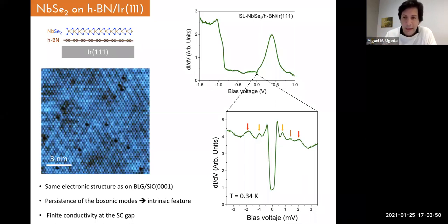The only difference is that in this case, we are unable to reach zero value for the conductance inside the superconducting gap. And we believe the reason for that is that we have two channels in the tunneling current, one of them to niobium diselenide, and we are close enough to the iridium so that we tunneled. So we believe this conductance comes directly from tunneling to the substrate. But other than that, the system behaves in a similar way.